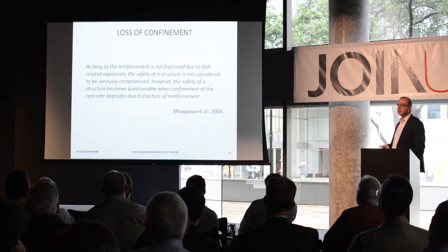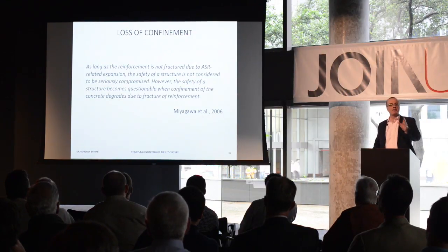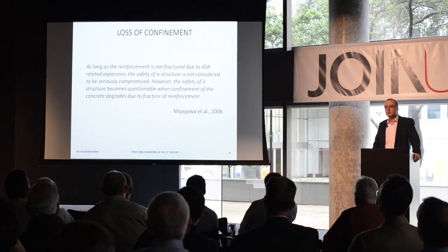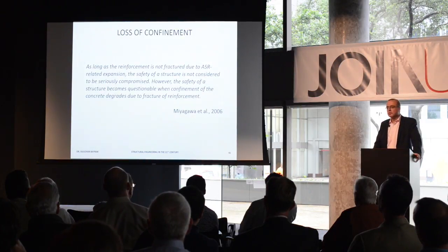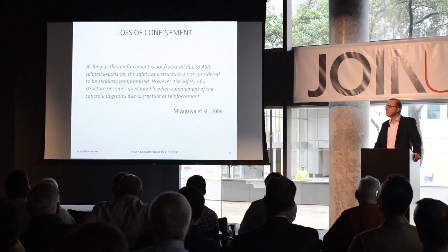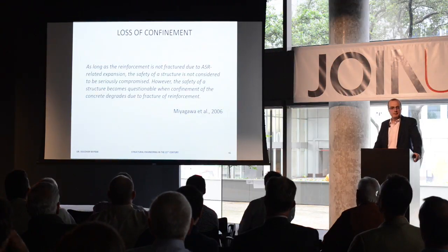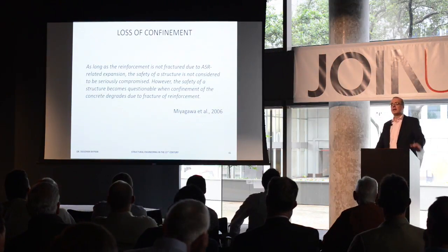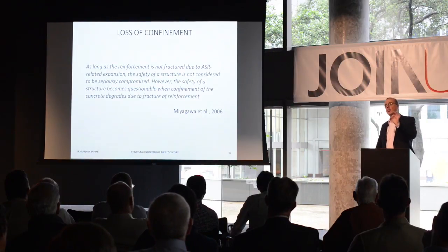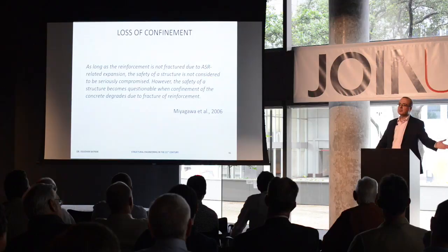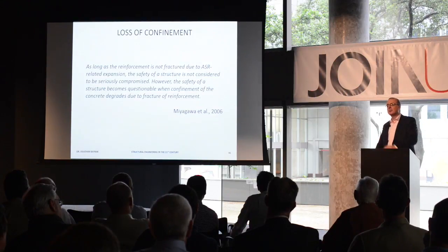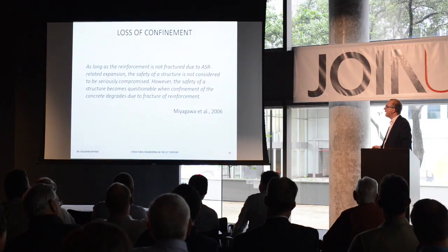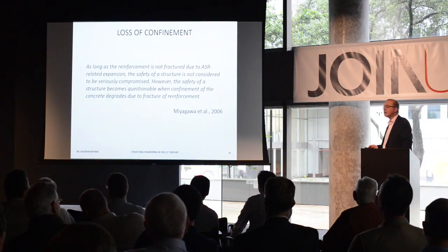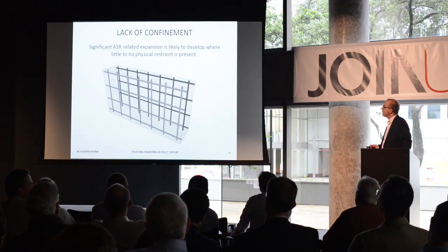So looking at the conclusion of Miyagawa, I will just say it's a very simple conclusion. Japanese researchers concluded that you don't have a problem until you do. It's absolutely not a problem. And then when and if rebar fractures, you go from not having a problem one day to having a lot of problem the day after that. So it's a bit of a tricky problem that requires continuous monitoring and significant insights into it.